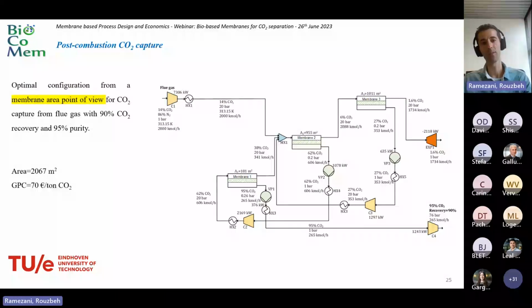But in this structure, we decided to see how it looks if, instead of having gas separation cost as the optimization target, we reach that target at the minimum membrane area. So here is the optimal configuration. You see the membrane area is much less compared to the previous one, which was 6,000. Now it is 2,000, but of course the cost is higher, 70 euro compared to 59. So if membrane area is your objective, you can reach your separation target at higher cost, but at lower membrane area.